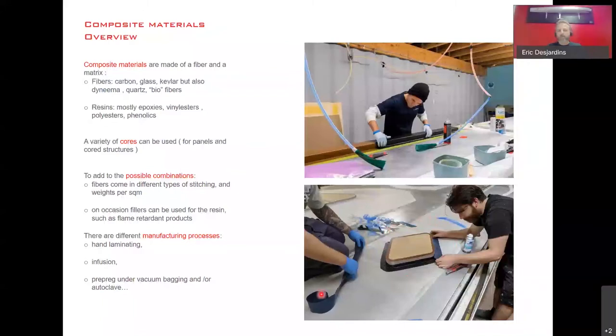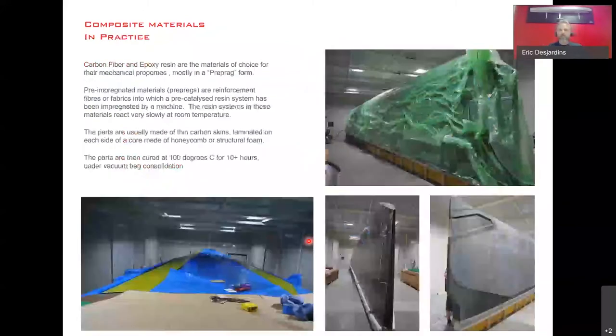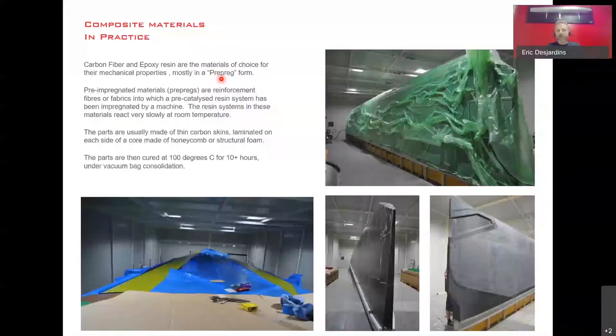So your head is probably spinning with all the ways of using composite material. It's very simple in practice. We're using carbon fiber and epoxy resin, and 80% of the time we use that in a prepreg form, which is where the resin and the fiber are mixed by a machine. You've got the perfect ratio between the fiber and the resin, which has a catalyst in there that reacts very slowly at room temperature. I'm talking about 2 weeks before the reaction really starts, so it gives you plenty of time to manipulate that prepreg fiber.